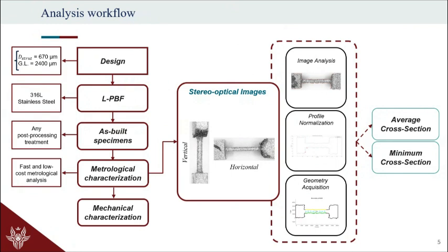and we took two images. One is the horizontal one that you see there, and the other one is the vertical one. We combine the two and make the hypothesis that we are actually looking at an ellipse from two sides. And we can build the ellipse again, basically taking the measurement of the two main axes. Of course, this is a simplification. This is not like having a complete 3D CT reconstruction, but this is very cheap and very fast. We can do it in the same approach for all these three directions of building.